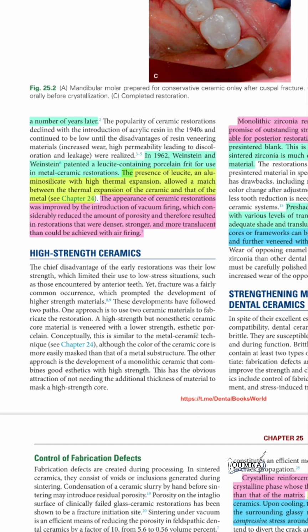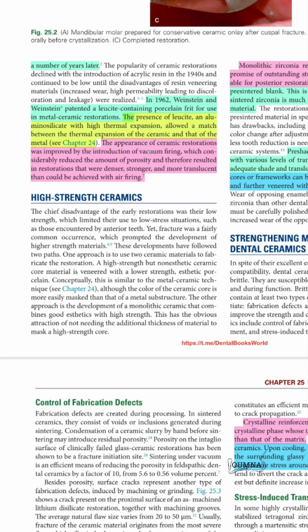In 1962, the addition of leucite to porcelain made the metal ceramic restorations applicable. The presence of the leucite, an aluminosilicate, with high thermal expansion allowed the matching between the thermal expansion of the ceramic and the metal. After the introduction of the vacuum firing, the porosity of the ceramic was reduced and we got denser, stronger and more translucent results.